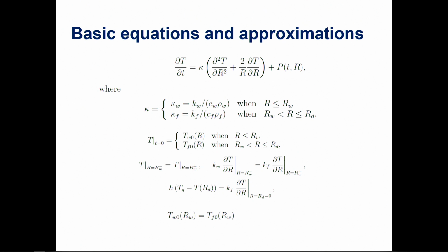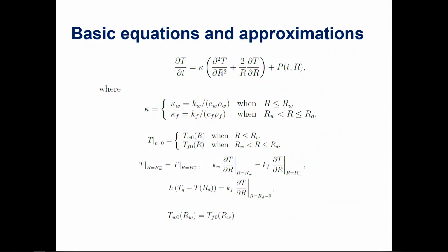In the general case, we use a source term due to thermal radiation, but eventually we are going to assume that this term is equal to 0, okay? And then in this equation, we took into account the existence of two layers, that is the layer of water and the layer of fuel. Also in the general case, we took into account the difference between the distribution of temperature in the water and temperature in the fuel. And we also use a set of boundary conditions at the interface between water and fuel, and also a typical boundary condition at the surface of the droplet.